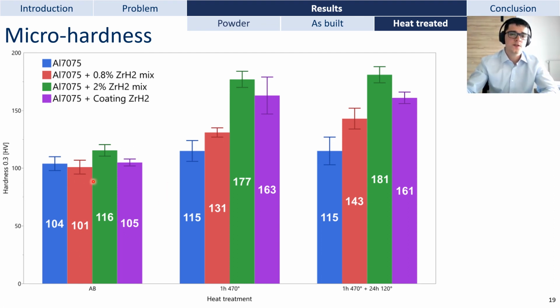First of all, we can notice that for the as-built condition, there is not much difference in the hardness for the 4 alloys. The second thing to notice is that there is not much difference between the solution heat treatment and the complete T6 heat treatment. It is a bit strange because normally it's the aging step that brings the high strength of the aluminum 7075. But since there was not much difference in the microstructure, it supports our observations.